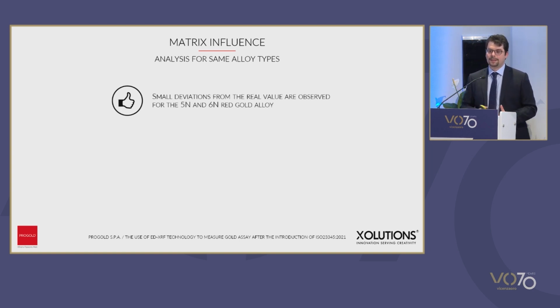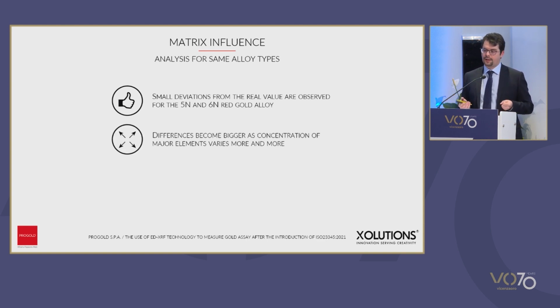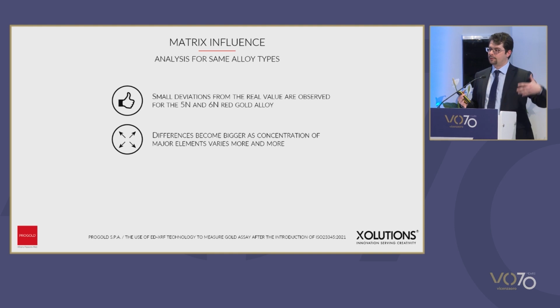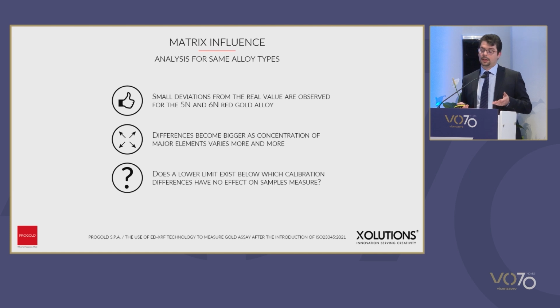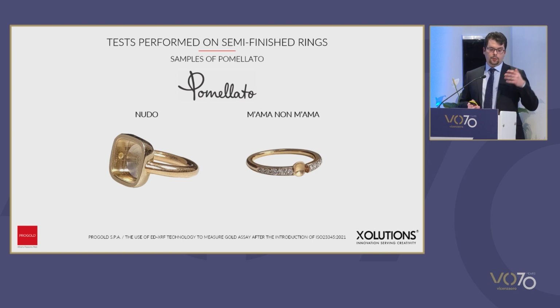That for small deviations from the real value, we have results which are in line with the previous ones, while as compositions differ, our results will worsen gradually. We still have to establish whether there is a lower limit which requires a more systematic test. That is, what can be the difference between the compositions used, and that in order not to excessively affect the